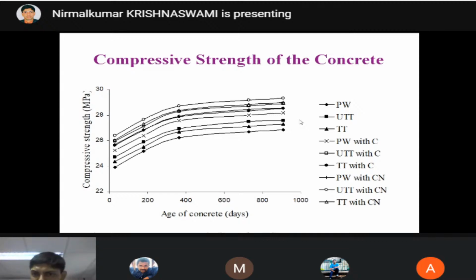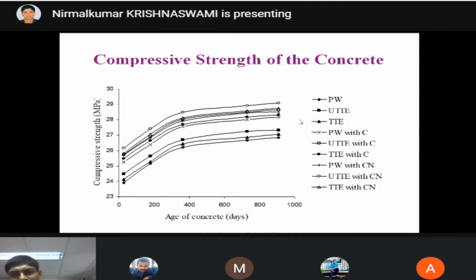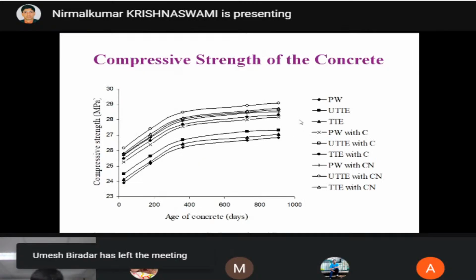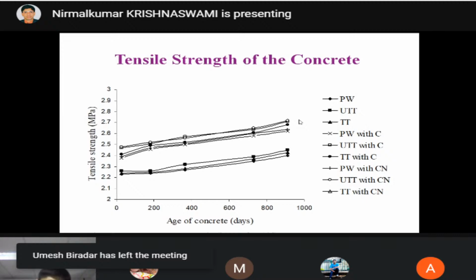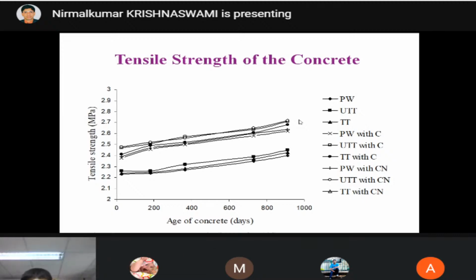This is for tannery effluent. The next slide shows the comparison for the textile effluent. Here also there are not many issues. So as far as compressive strength is considered, it is good. Then let me go to the tensile strength. Once the compressive strength is good, obviously we will have good tensile strength, but I could not take a chance, so I determined it using specimens. Here there is not much variation. The minimum is 2.2 Newton per mm square and it goes to 2.7 Newton per mm square. Even with the addition of admixtures, it is not much variable.